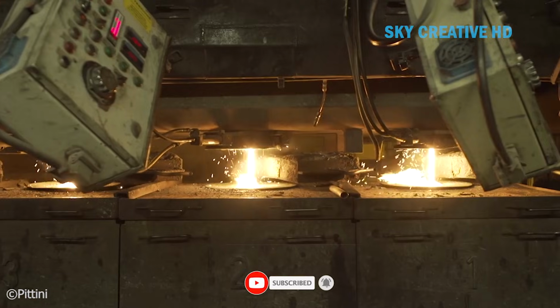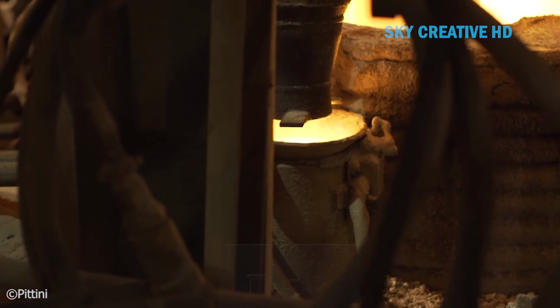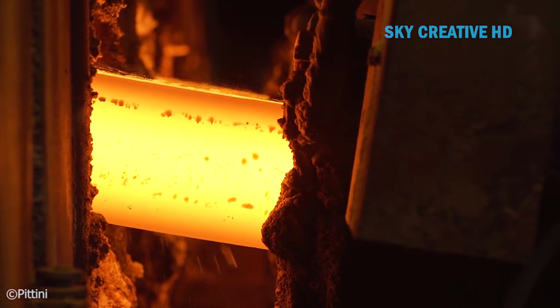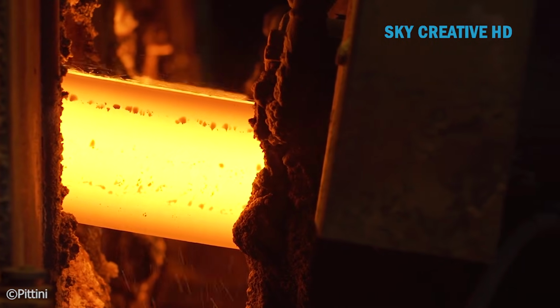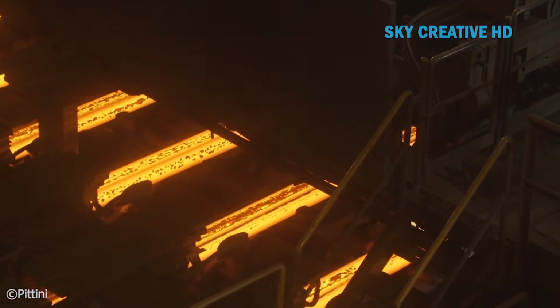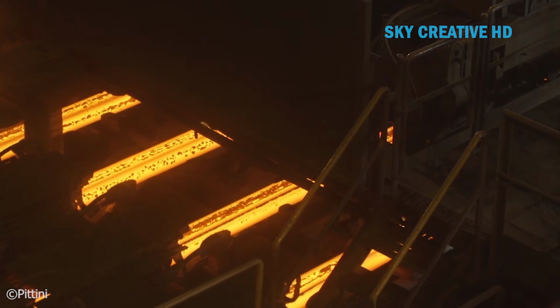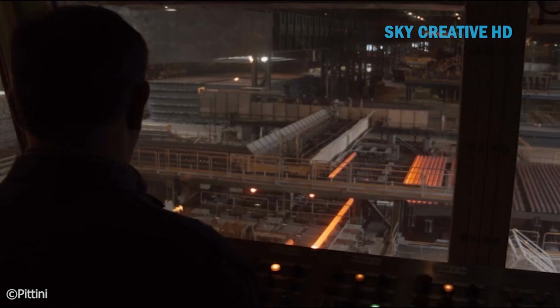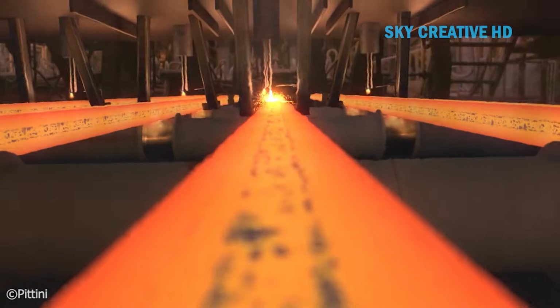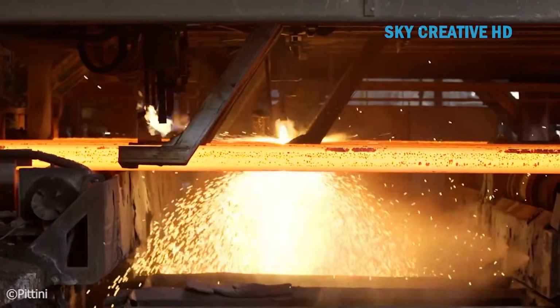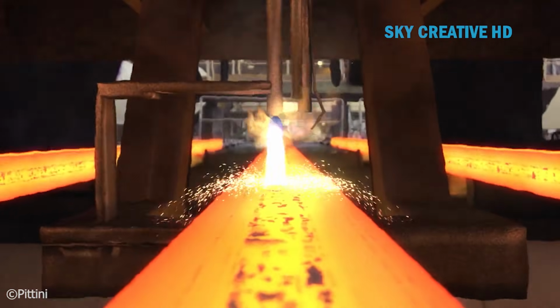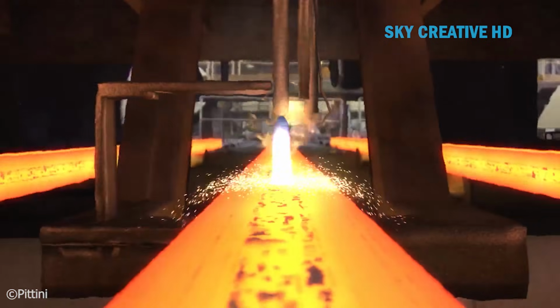As the wire rod exits the final rolling stand, it enters a cooling system. Pittini uses what's called controlled cooling, where water sprays and air jets bring the temperature down in a precisely managed way. This isn't just about cooling it off. The cooling rate actually determines the final properties of the steel. Cool it too fast, and it becomes brittle. Too slow, and it might be too soft.